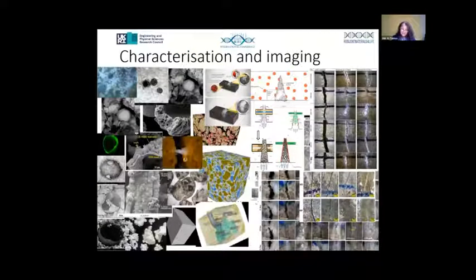We use multiple techniques for the characterization and imaging of the materials and products themselves, and when they are placed within the cementitious matrix. Particular areas of focus have included survivability during the mixing process. For example, do the microcapsules remain intact? Good distribution within the mix, particularly when working with nanomaterials. And then effectiveness of the bonding with the cementitious matrix, which obviously governs the triggering mechanism. We've also used those techniques to follow the triggering and the self-healing process, so looking at rupture mechanism, crack closure, release of cargo, or rebar corrosion.